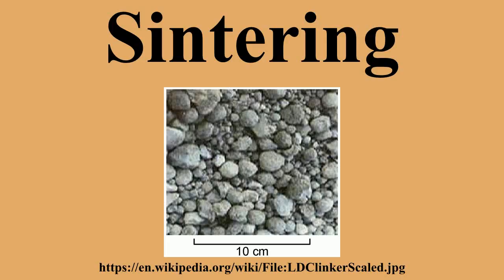Liquid phase sintering. For materials which are difficult to sinter, a process called liquid phase sintering is commonly used. Materials for which liquid phase sintering is common are silicon nitride, WC, and more. Liquid phase sintering is the process of adding an additive to the powder which will melt before the matrix phase. The process of liquid phase sintering has 3 stages. Rearrangement. As the liquid melts, capillary action will pull the liquid into pores and also cause grains to rearrange into a more favorable packing arrangement.